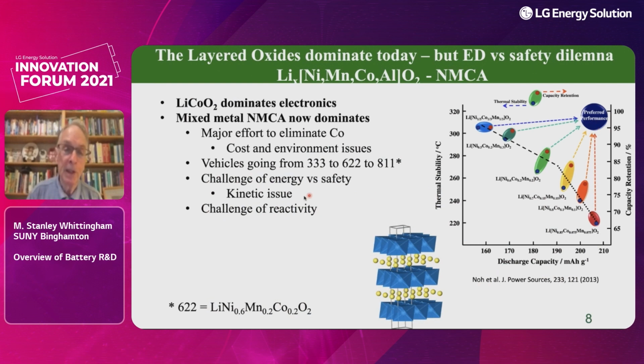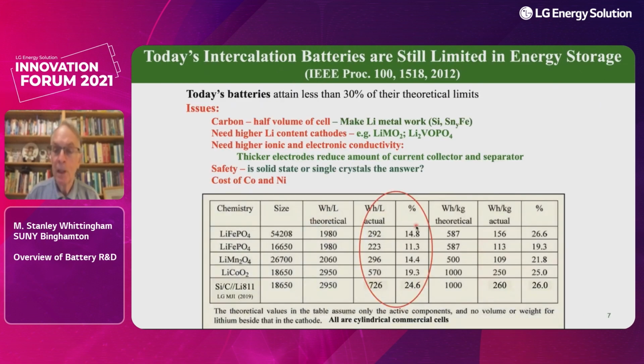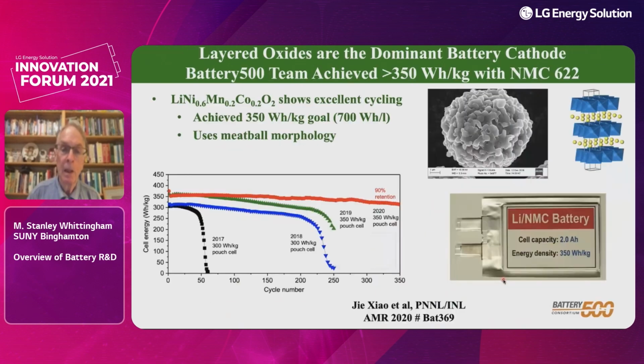So as I mentioned, the stability is really a kinetic issue. If we can somehow stabilize the lattice so the ions other than the lithium do not move much, it should be more stable. So we are presently studying the reactivity of these materials. And the Battery 500 project is in particular looking to get the energy density of these materials up from this 250 to 260 up to 500. And I'll show you the latest data in this slide.